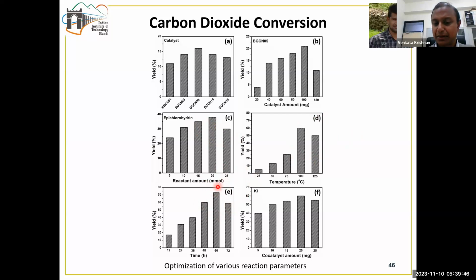Although we can see that the timing of the reaction is increased, which is about 60 hours, but given the condition that we are not using a pressure reactor and we are doing the reactions at atmospheric pressure conditions, this is quite a good achievement, I would say. And we also improved the catalytic activity by adding a co-catalyst. In our case, we used potassium iodide as the co-catalyst, and we found that adding about 20 milligrams of the potassium iodide co-catalyst further improves the yield of the reaction.